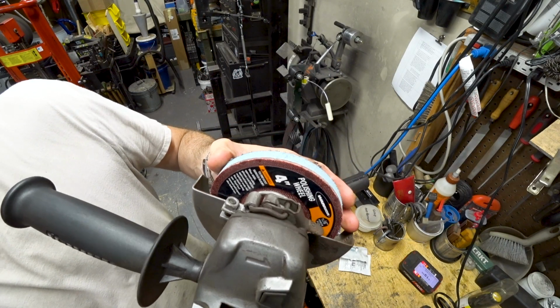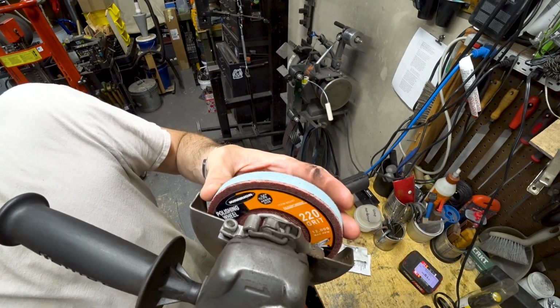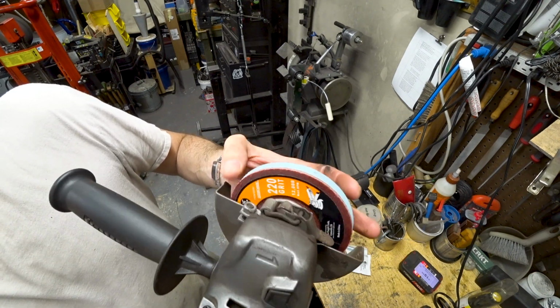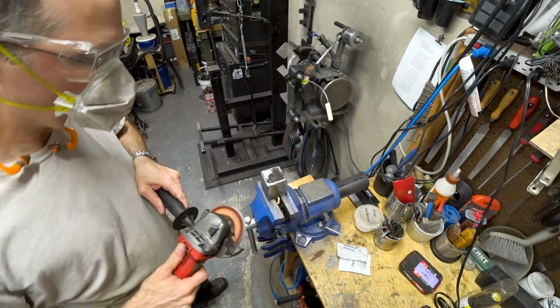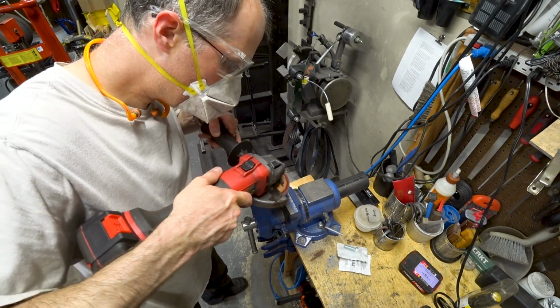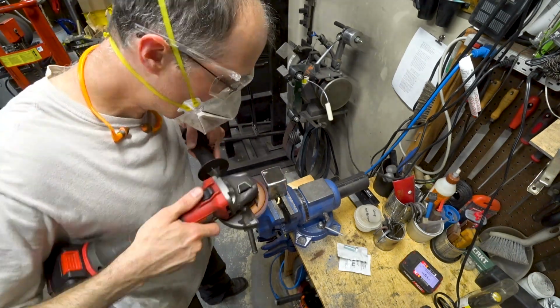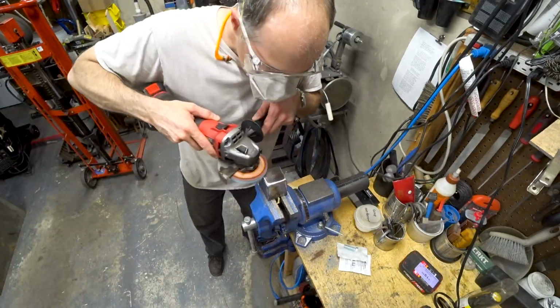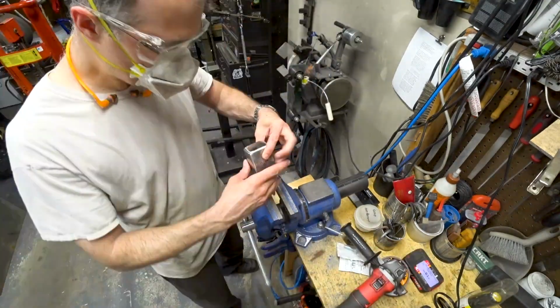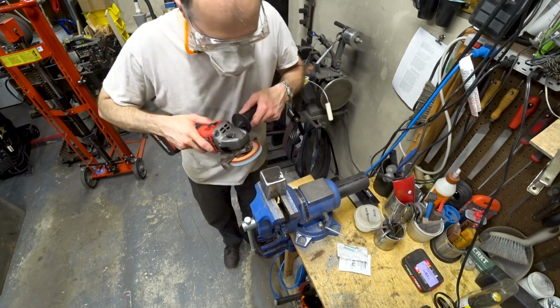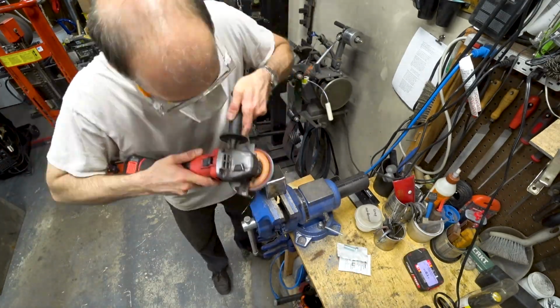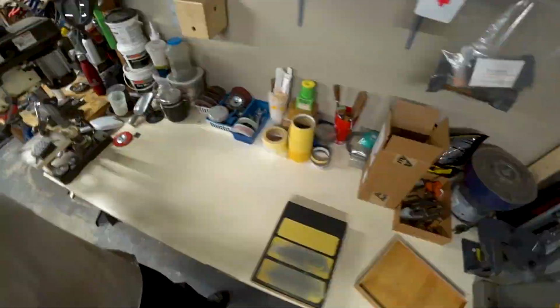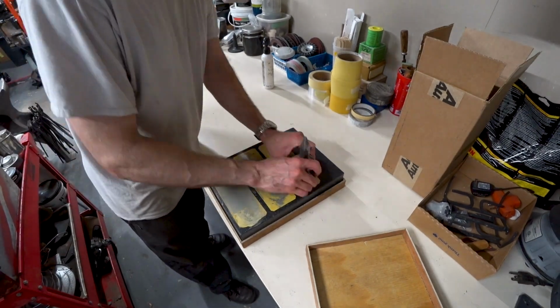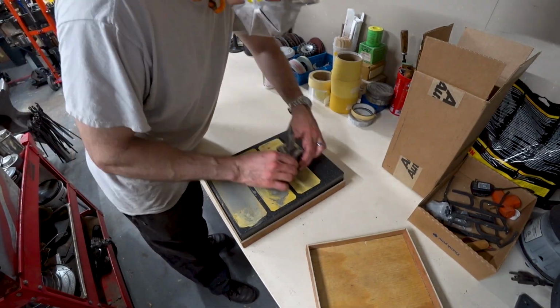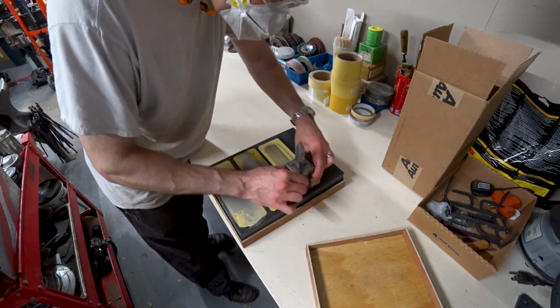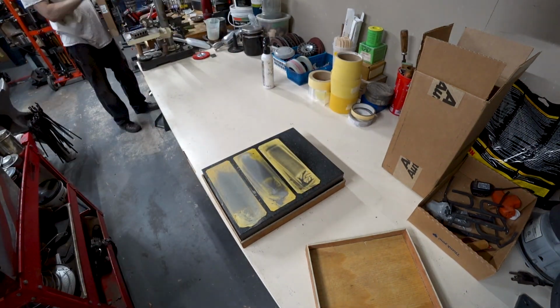This first little bit of footage actually was shown in the last video, but I wanted to recap. Basically, if you're going to do a case hardening on something, you need to make sure that it is already prepped and to dimension, because you don't want to have to do any grinding, or at least very little grinding. Otherwise, you're just going to grind through the case. It's only going to be about a millimeter or two at most. Now that I'm happy with the grind and polish on this, we can start the case hardening process.